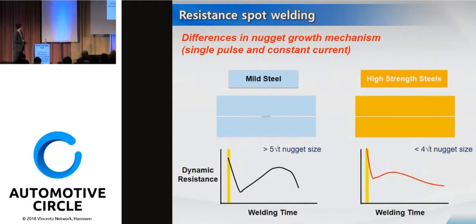Here's the animation in here. So it starts with welding time, grows until the end of the welding time. It grows into a relatively large nugget diameter. In case of high-strength steel, if you look at the dynamic resistance curve in here, actually with the very high initial contact resistance, and then the peak of the heat generation is very quick here. So heat generation is very quick at the early welding time, and then no more growth of the welding nugget. Here's the animation for high-strength steel.